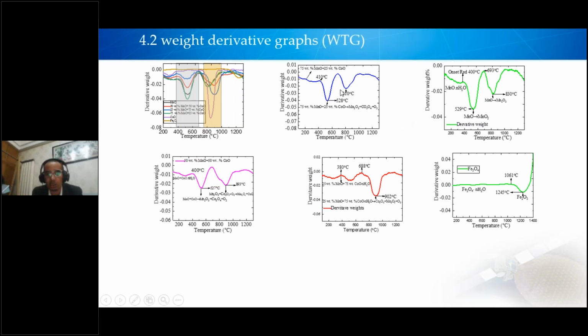Anyways, from this weight derivative we see the phase changing temperatures, and these phase changing temperatures are real, so we can check them in the XRD. Otherwise, among these phase changing temperatures, iron occurs at higher temperatures than any other. The other compositions mostly have the first reduction between 400 and 500 degrees centigrade.